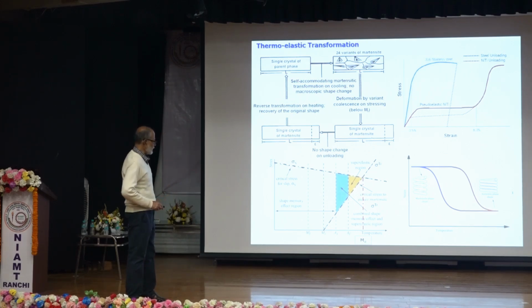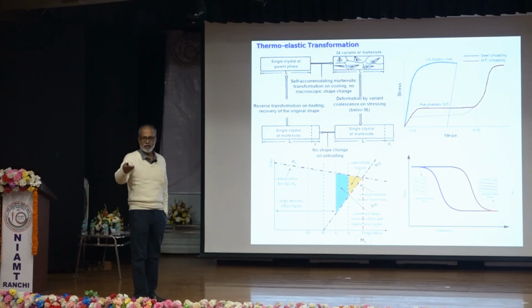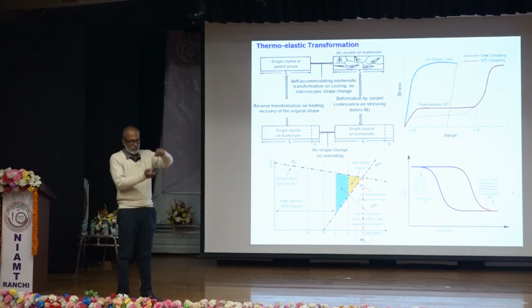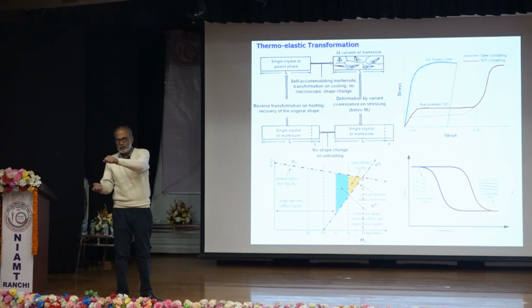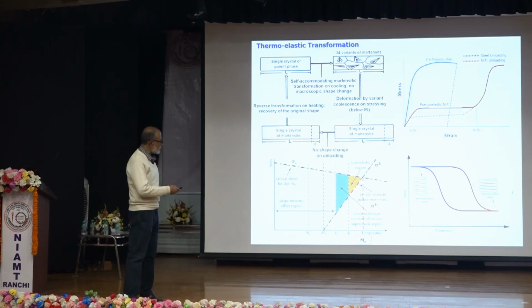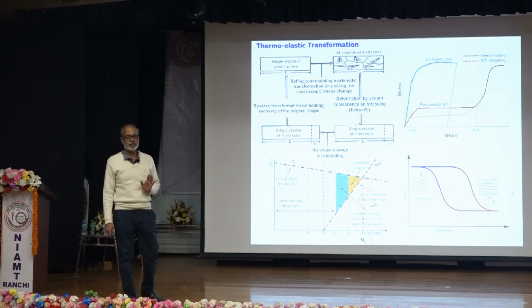But imagine you have two springs of two different dimensions, right? At martensitic temperature, you give a shape to the spring. Heat it at austenitic temperature. You give another shape. And maintain these shapes at these two temperatures and continue this cycle n times. 10 times, 20 times, 30 times, you do this. Take it into martensite, give it a length, heat it up at austenite, compress it, give it a length. Do this for 20 times. After that, you just change the temperature. The material will attain this particular length at martensite, and this particular shape at austenite without application of any strain.